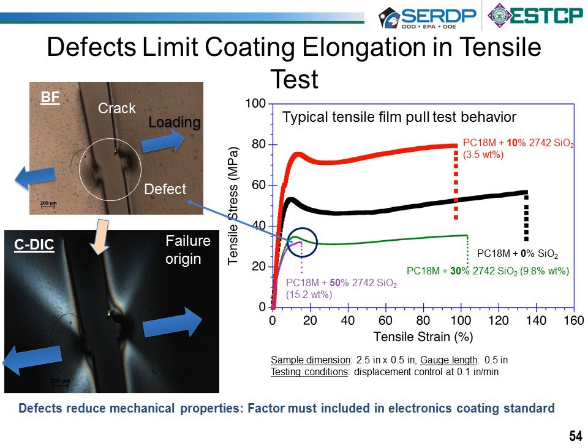We tried to further define what the criterion might be for a coating with good whisker mitigation effectiveness. Part of that task, in addition to looking at the microstructures, was trying to tie those microstructural aspects to the mechanical characteristics. So one of the things that we did was to develop films on which we performed tensile testing. One of the things we noticed right off is that we had a fair amount of variation from sample to sample, and we saw bubbles in some of the films that resulted in crack initiation sites, which limited the elongation.